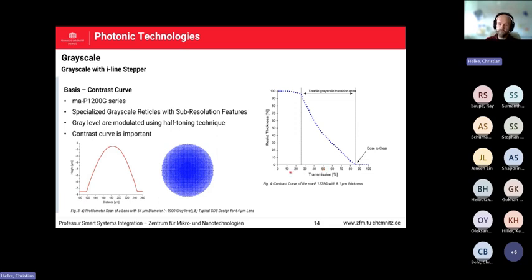And so one has to do some contrast curve measurement. We have a resist with a certain thickness here, and then we expose the whole wafer or the whole photoresist with a certain contrast curve, where the dose is modulated by a transmission in 1% steps. Afterwards one can characterize these and see, okay, in the range here of 25 to 85% transmittance, we have something like a linear fit in between, and so we know 50% transmission will result here in 40% of resist thickness, whereas with 25% transmission, we have nearly 100% resist thickness. This information goes directly into the modulation of the layout data which is needed for the mask. And with this one can realize the 3D structures quite well.